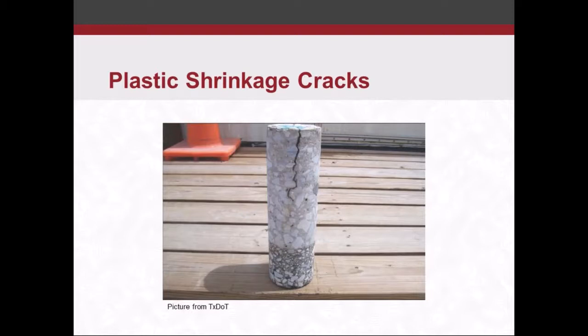So this was a core that was taken out of a plastic shrinkage crack, and you can see it's pretty much halfway through, maybe more than halfway through this core section here. Looks like probably a 12-inch thick concrete, some pretty large aggregate. And down here at the bottom, it's kind of weird to see asphalt at the bottom. A lot of times, or at least here in New York, we'll see an asphalt overlay on concrete. We won't see the asphalt down here at the bottom.